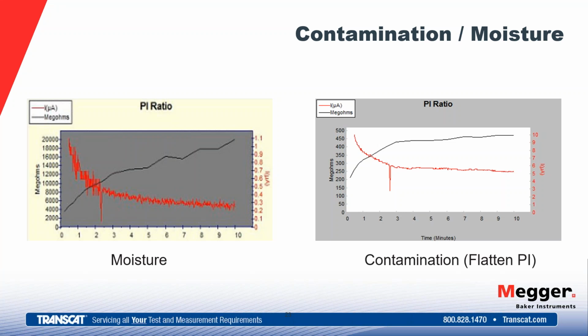It could also be contamination, as we see on the right, not so much moisture, but the flattening of this curve is indicative of contamination. Basically, we would see this insulation continue polarizing if that contamination wasn't there, and the contamination holds it up. Again, those parallel paths to ground keep the current high, even though the insulation may be polarizing.